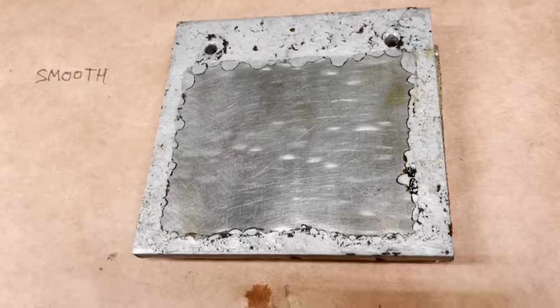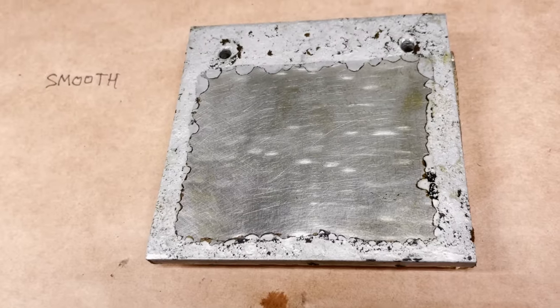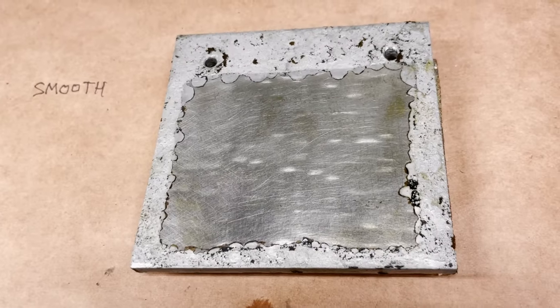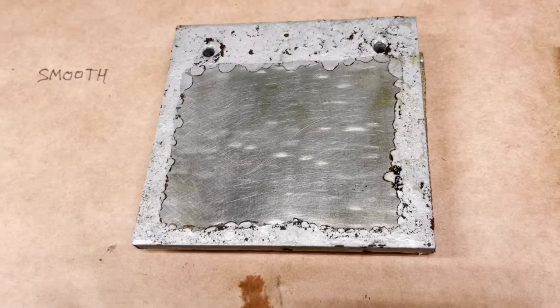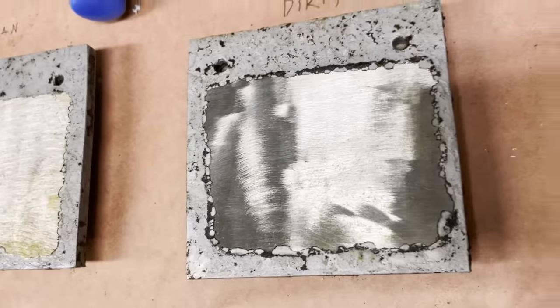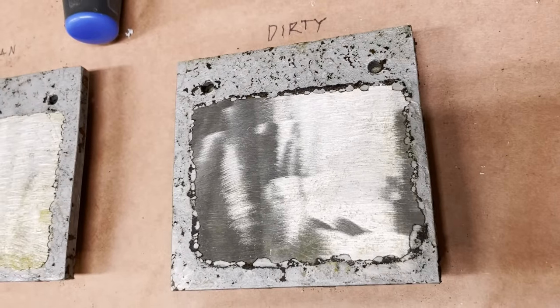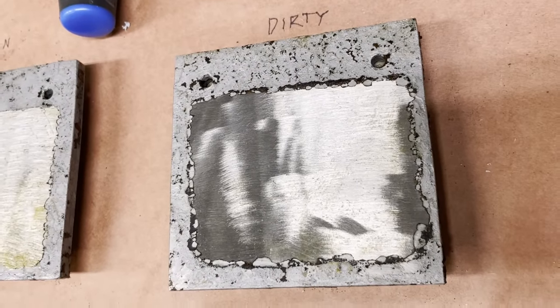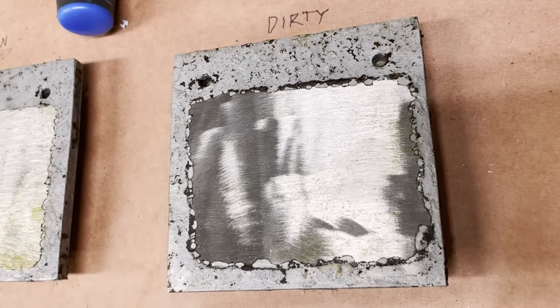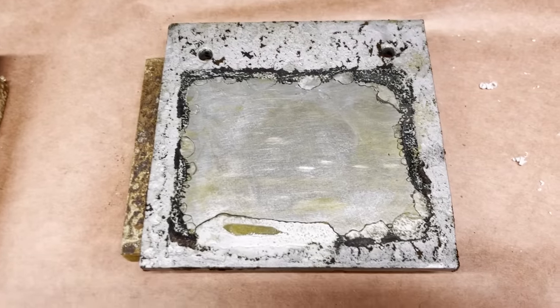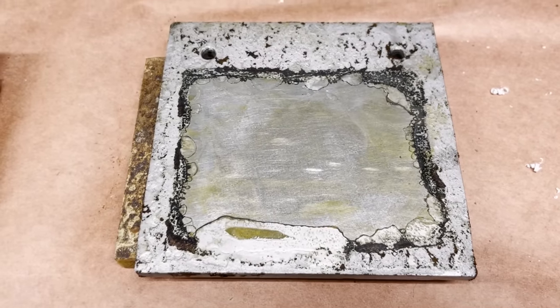The smooth and clean sample had much more rust under the edges of the coating that you can see in these semicircular areas protruding into the coated area. Similarly, the roughened yet oily sample had those semicircular intrusions of rust all around the perimeter of the coated area. The smooth and dirty sample was, as expected, the worst of them all.